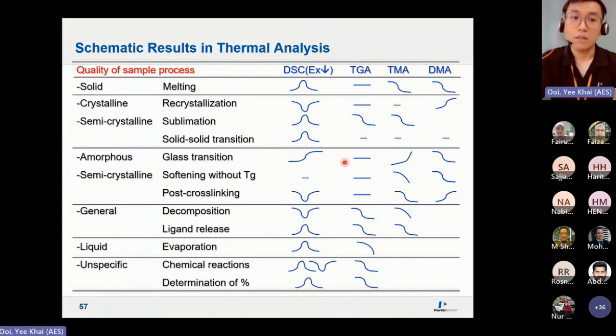So how is the data usually represented in DSC? You are going to get a curve like this, for example. The glass transition is always a step increase in baseline, like a staircase. This is usually not a very strong transition. It's just a step increase like this. And this is why, if you want to get a very good reading on it, it's always recommended to use a standalone DSC.